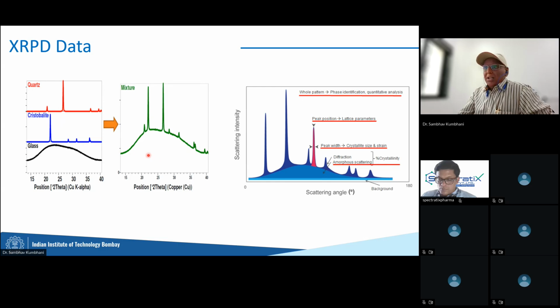Okay. So you can imagine, right? In your mind now, you can clearly see that this big hump must be the glass, and this big peak over here is this peak. This big peak over here is this peak. From that information, if you want to backtrack, you can say, oh, this has these three materials in it, and essentially that is what we do in XRD in real life also.